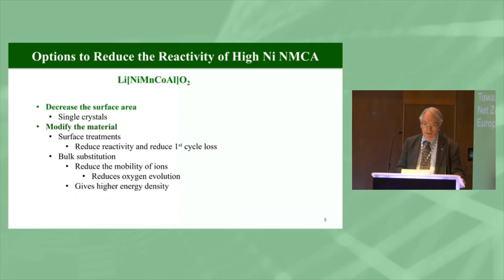So how do we reduce the reactivity? There's several ways. One is to reduce the surface area. If we have one big single crystal, it's going to be very little surface area. It's going to be not reactive, but you're not going to get much power out of it. So there's clearly a trade-off. But I'll show you in a moment, there's a big push now to go to single crystals. A second way is to modify the material to reduce its reactivity, and that's where niobium comes in. I'll talk about that. Another way is to substitute in the bulk of the material and reduce the mobility of the oxygen ions so they can't be evolved. If we do this, we should get higher energy density. And I'll talk about this first cycle loss in just a moment.